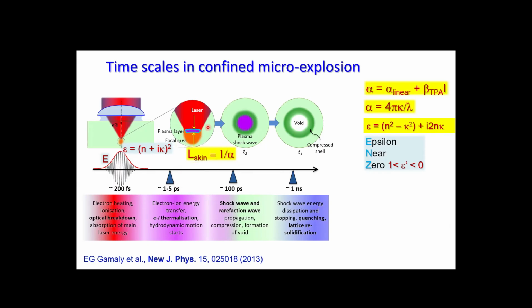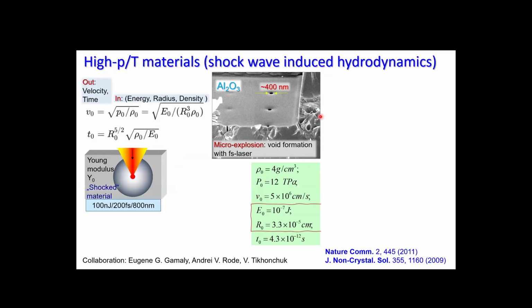The most dramatic damage of material you can write inside would be a void, which you form by micro explosion. This is an example with a few numbers, and it's only one kind of tutorial slide. So a void indeed can be created, and when we saw it formed in sapphire, it was kind of interesting. We are focusing below the surface, and pulse energy is around 100 nanojoules. We are focusing to a focal spot which is close to the wavelength. An 800 nanometer laser was used here.